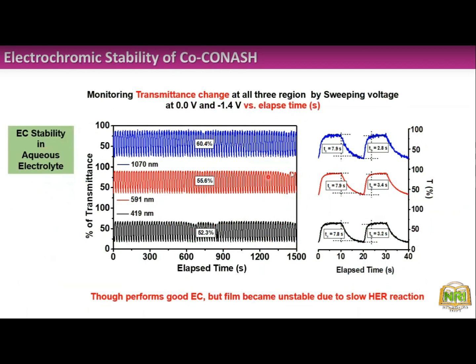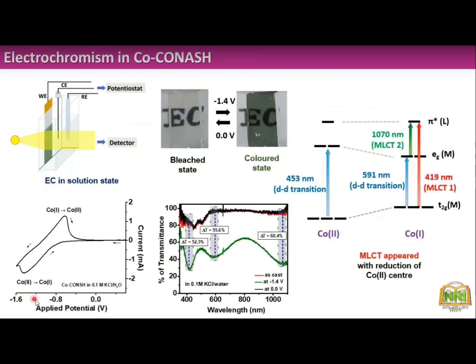This is because as we are applying almost minus 1.6 volts or minus 1.5 volts, this is the region where water will split. Water will split, and the hydrogen evolution reaction will happen at that particular voltage. So as the hydrogen evolution reaction goes on slowly, after a certain time the film will come out from the ITO substrate, and there will be degradation of the film.